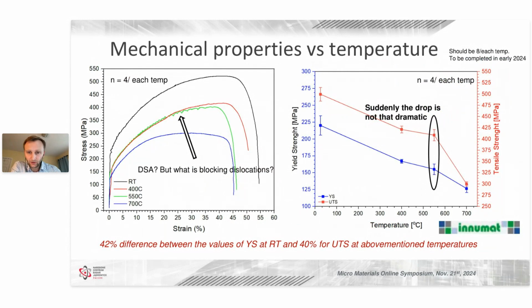And again, at a certain temperature, we saw very similar results as with nanoindentation in the previous examples. When doing tests at 400, 550, and 700 degrees, we clearly see that only at one temperature the stress-strain curve shows some kind of discontinuities. There are certain bumps on this curve. At the same time, when we plotted mechanical properties as a function of temperature, we clearly see that suddenly the drop is not that dramatic at this temperature. So we believe that this is again dynamic strain aging, which is caused by solute atoms. We are doing precise chemical analysis of the alloy right now to understand on the ppm level what is going on with this material.